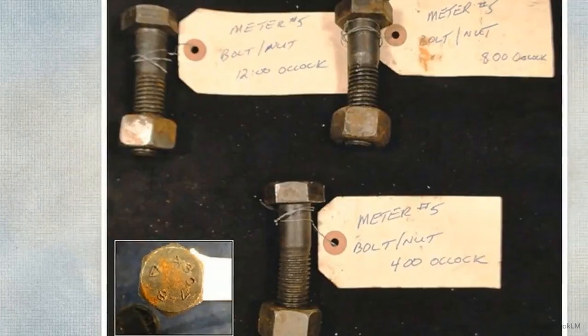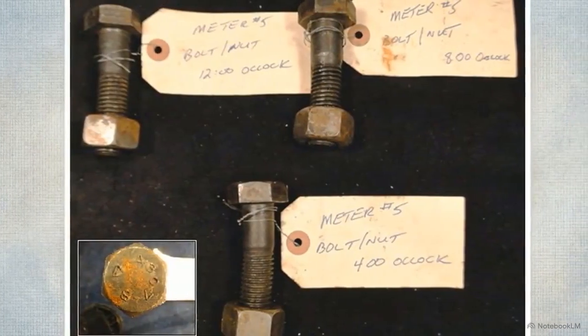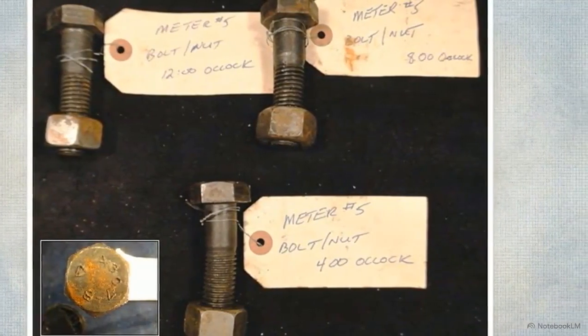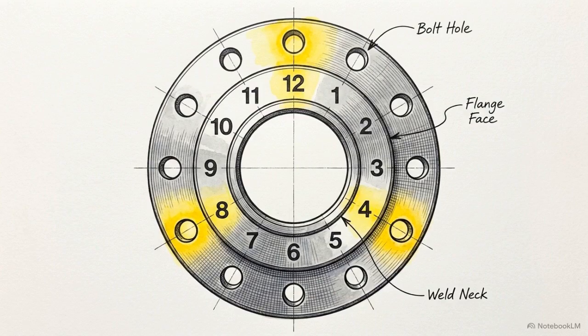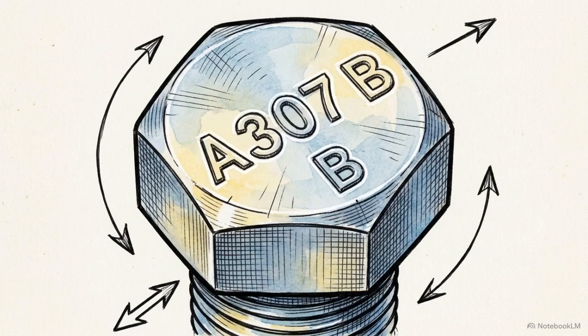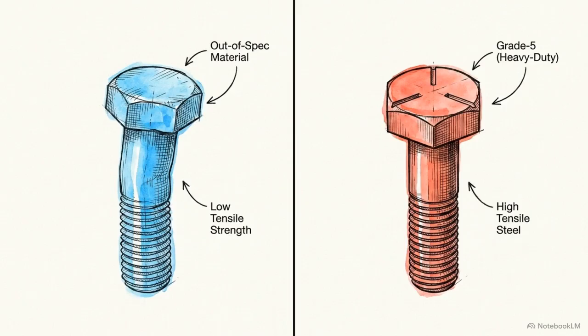This photograph documents a second, distinct set of hardware recovered from the exact same flange. 3 intact but severely deformed fasteners were pulled from the 12, 8, and 4 o'clock positions. The head markings on these deformed bolts reveal they are ASTM A307B standards. They belong to a completely different, lower-grade material specification than the grade 5 bolts at the bottom.